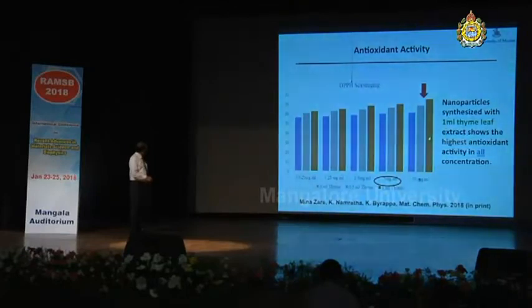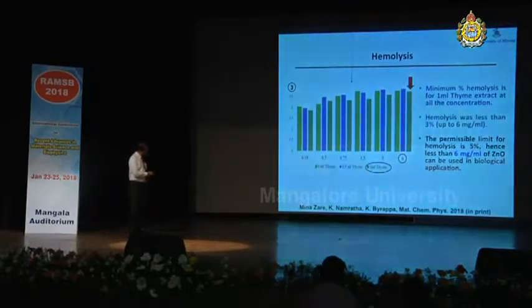And this shows the nanoparticle synthesized with 1 milliliter thyme leaf extract shows the highest antioxidant property compared to all the others, in all the concentrations. So that is the result of thyme. And now a hemolysis study has been carried out for the same thyme leaf extract used zinc oxide, and we have obtained minimum percentage hemolysis, and these are very good results.